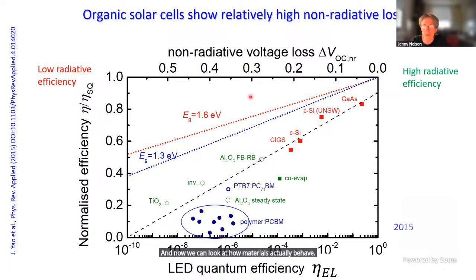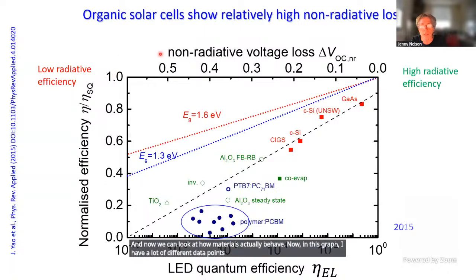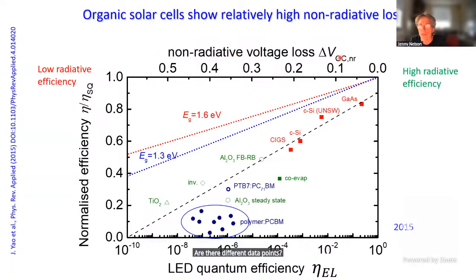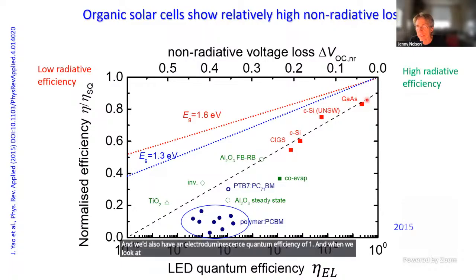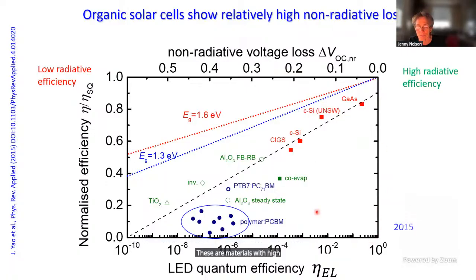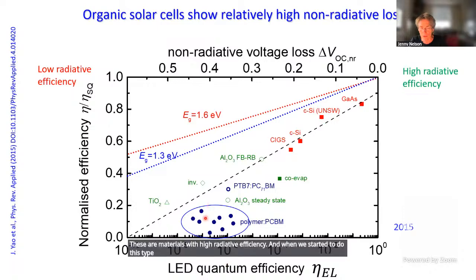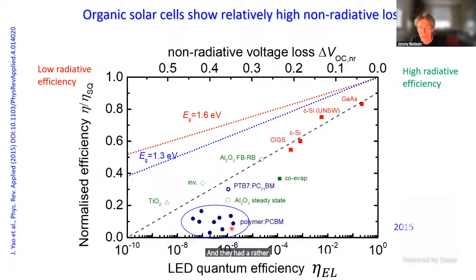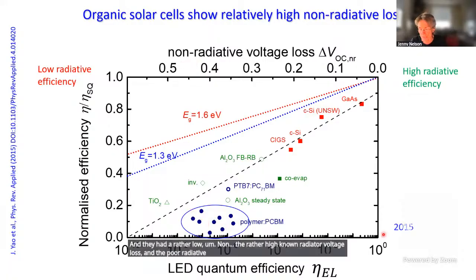Now we can look at how materials actually behave. In this graph, I have a lot of different data points, and what I'm showing are the different data points as a function of this quantity that I just defined, the non-radiative voltage loss. So the ideal solar cell would have a zero loss. It would be over here at the right, and would also have an electroluminescence quantum efficiency of 1. And when we look at different materials, we see gallium arsenide, the best material, is over here. These are materials with high radiative efficiency. And when we started to do this type of analysis on organic solar cells, they were actually performing quite badly. They had a rather high non-radiative voltage loss and a poor radiative efficiency. This is back in 2015.